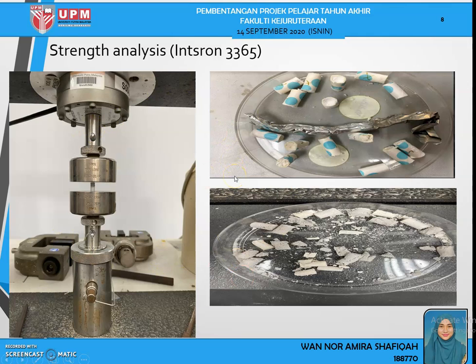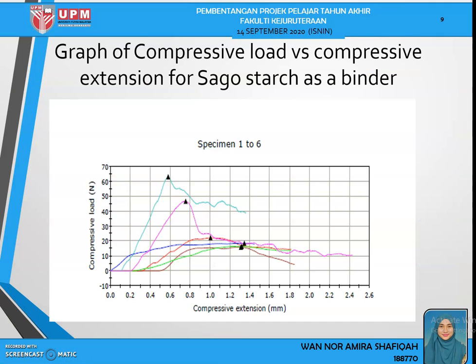We also did the strength analysis using the Instron 3365 in the mechanical lab. So this specimen is 10 times 5 mm. We dried it for 7 days. So this is the collapsed structure when the maximum load is applied. This is the graph of compressive load versus compressive extension for sago starch as a binder. Based on this table, the mean maximum load for the BG after being calculated is 30.5 Newton, with a compressive strength value of 1.56 MPa. We ignore these first two, and we only consider the three.